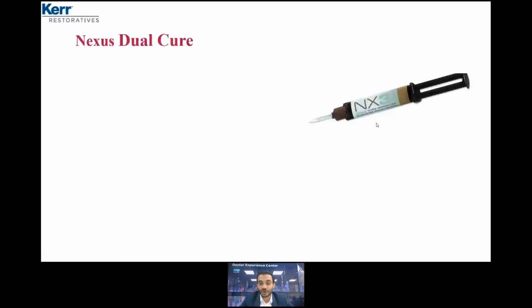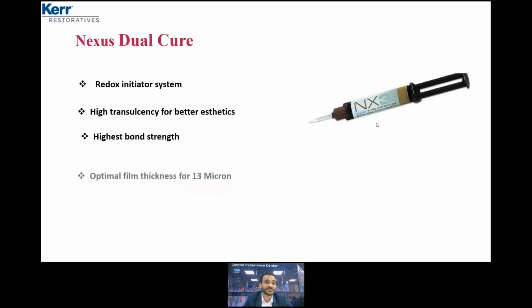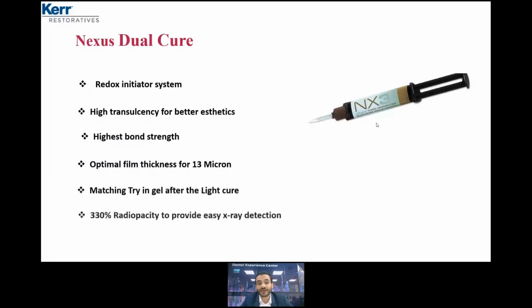Nexus dual cure cement is also one of the total adhesive resin cements. You can use it for veneer, yes you can, but again, practically it's a dual cure cement. It's better to use a light cure cement in order to control the working time. Same high color stability, high translucency, high bonding strength, optimal film thickness, matching to the try-in, high radiopacity, same points regarding the light cure. Both of them are similar. The only difference here in the dual cure cement, and once you try it you will see by yourself, is that the viscosity in dual cure cement is slightly less than the light cure cement, but the bonding strength for both of them, film thickness, radiopacity, almost filler load, all of them are almost equal.